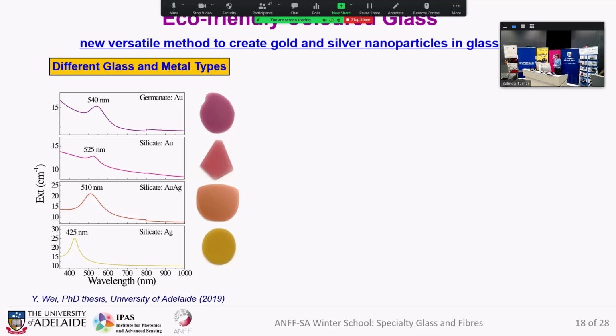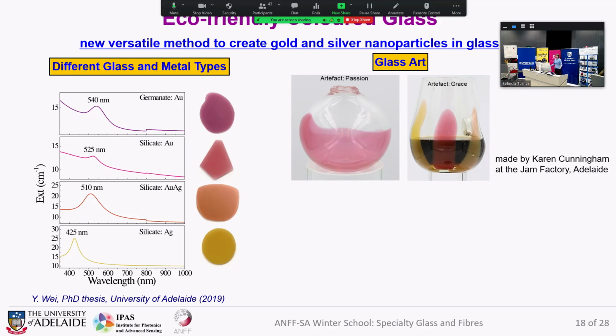We realized that by chance we invented this method for tellurite glass, but then we tested it for a lot of other glasses, and for almost all oxide glasses it works — you can see the different colors we can make. We then worked together with glass artists, because it became apparent that gold and silver nanoparticles give different colors.